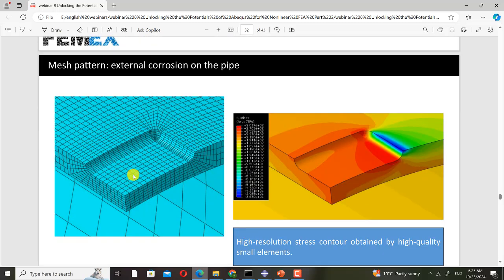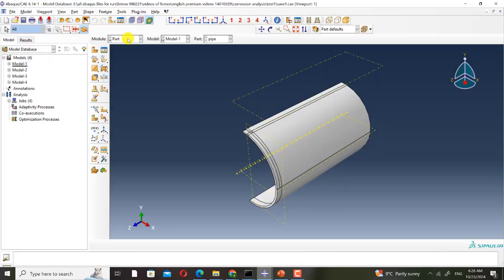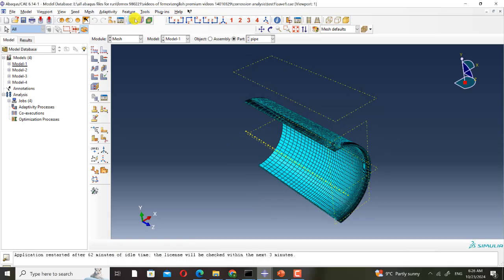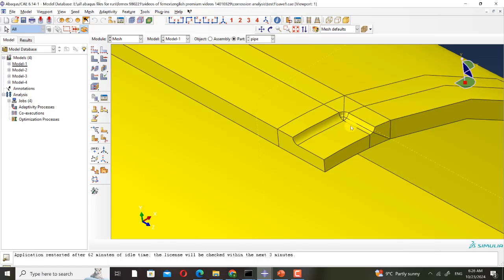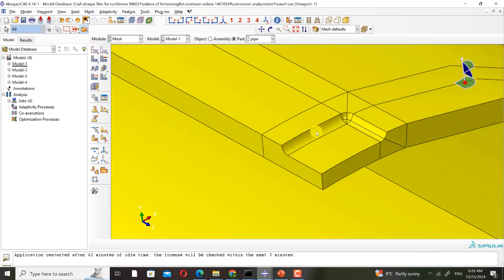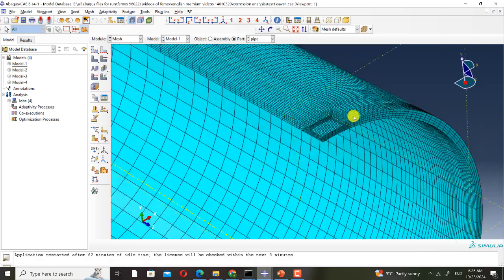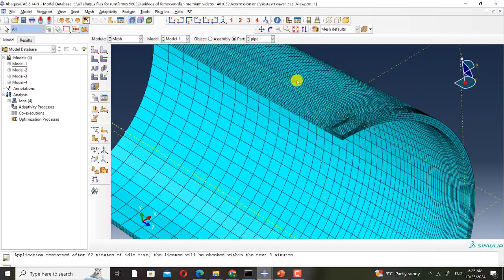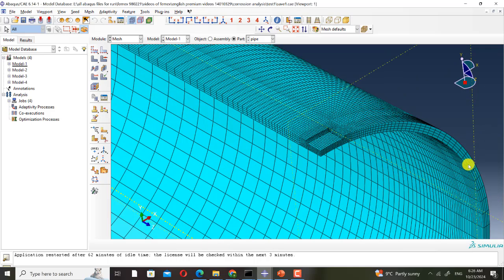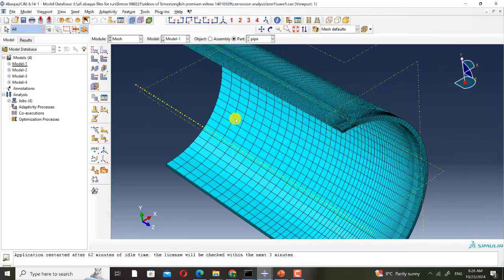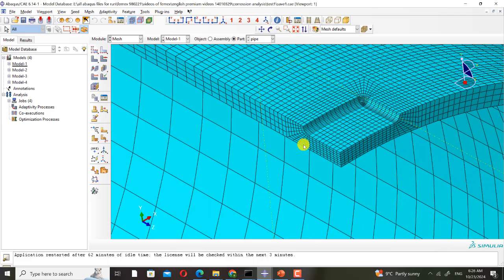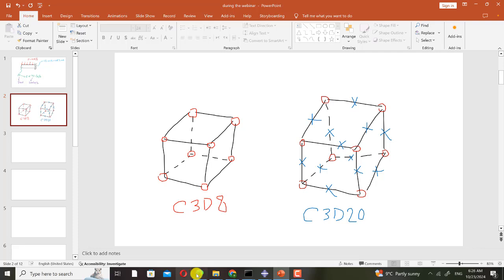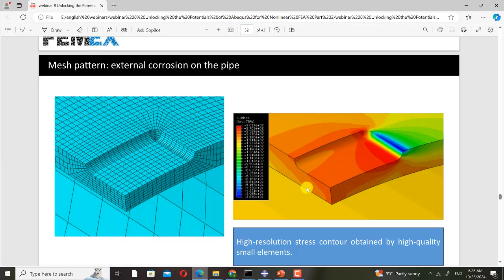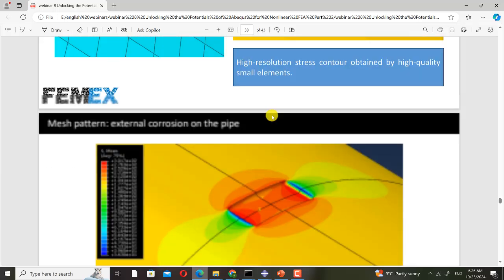And finally, you can see the external corrosion on the pipe example. Here we have it. I go to the mesh. Here you can see that I have used this kind of partitioning to be able to mesh it with hex elements. And I have tried to create mapped mesh in all of the regions, okay? But you can see that along this edge we have bias. Along this edge we also have bias, okay? So we have large elements here and small elements here. We use small elements here because we have a stress concentration. And here you can see that the stress concentration and stress gradients are captured accurately. Okay, that's it.